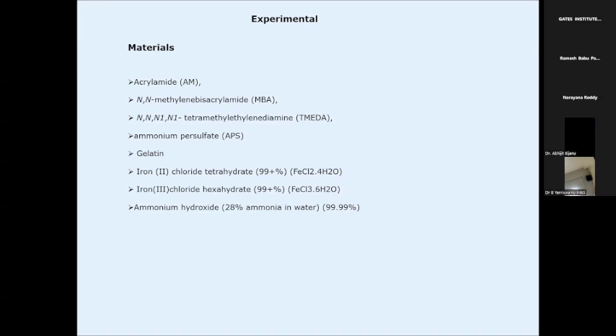So if you go through each individual one, acrylamide, MBA, and gelatin act as a monomer as well as polymer system, where you are converting your monomers into polymers, and MBA acts as a cross-linking system. See, these monomers are developing each chain. So to bridge the gap from one chain to another chain, you are using MBA. So how are you converting these acrylamide monomers into polymers? You have a catalyst system, ammonium persulfate and TEMED, tetramethylethylenediamine. This is actually a type of redox reaction, I can say, where we are creating free radicals by reducing with the catalyst. So it will start the initiation.